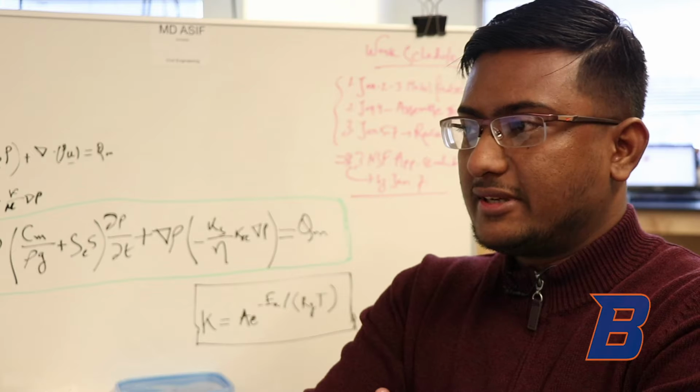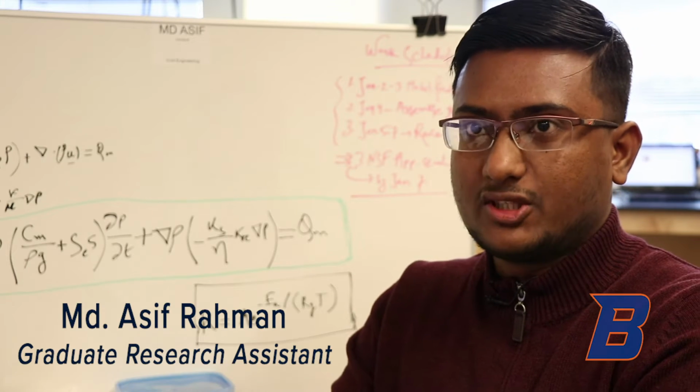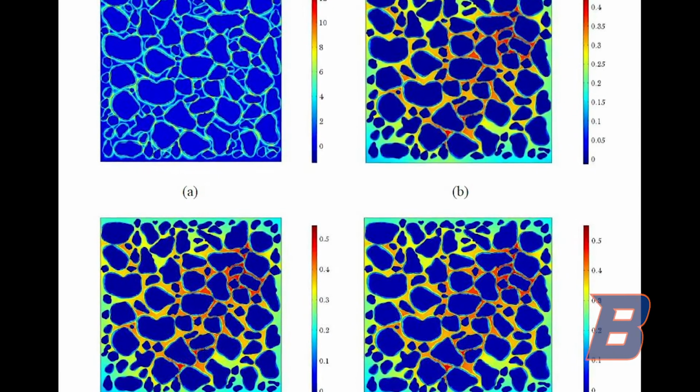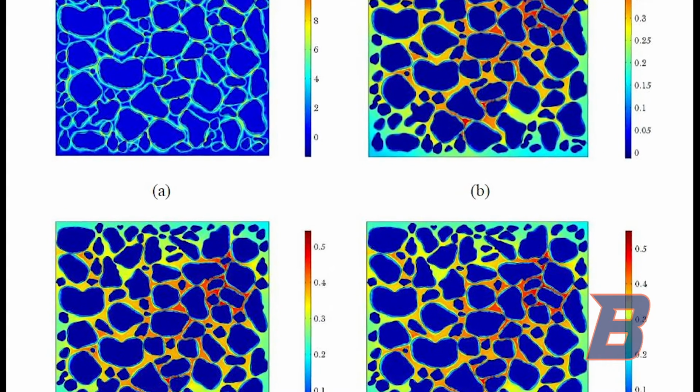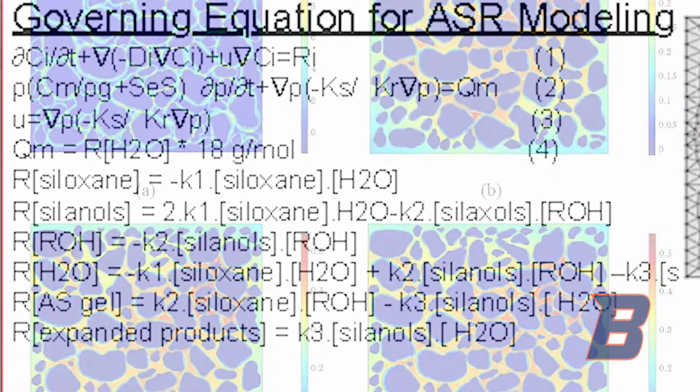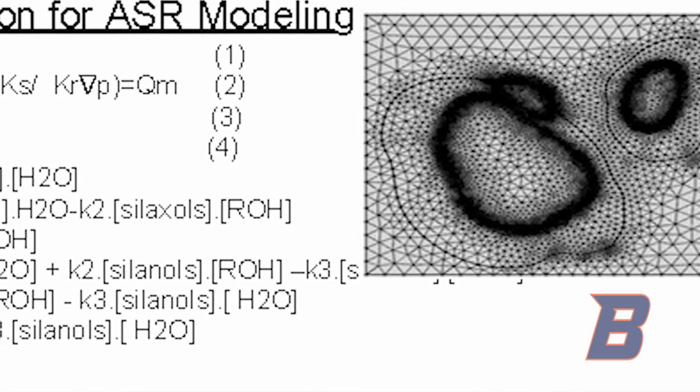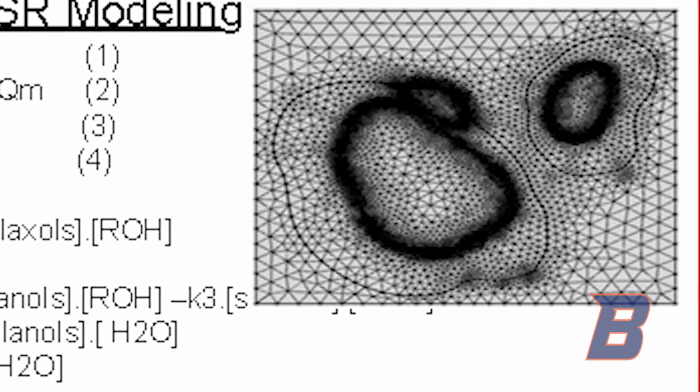Generally, for other degradation modes of concrete, you can stop them by blocking water and providing a better condition. But ASR is hard because it comes from inside. So basically these equations are a quantification of the ASR expansion, and the ASR expansion is a major issue in concrete structures. Several researchers are trying to find out the actual chemical kinetics in the concrete, because it is not possible to see or do any exact experiment on the concrete microstructure. So the basic idea is to develop several governing sets of equations based on those chemical kinetics and quantify the expansion mechanism in the concrete structure.